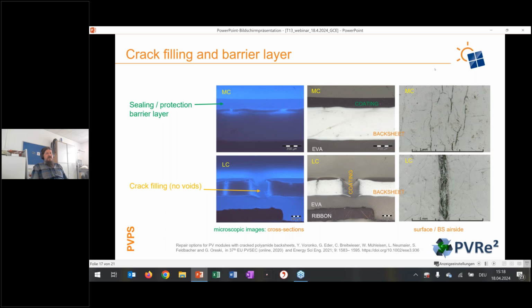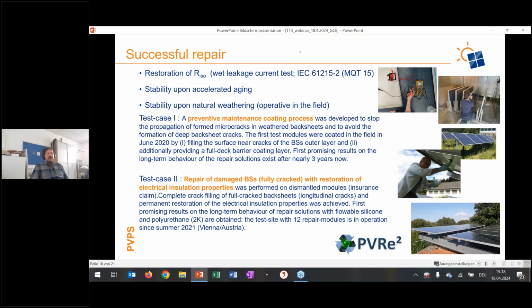As I already teased, we were successful. We could show that both of our coating solutions sealed the crack and also added an additional protection layer on top of the whole backsheet. So we really did the job there. We were successful, and additionally, we could also restore the wet leakage insulation of the PV module with that coating. The coating showed great stability upon accelerated aging tests, where we did especially damp heat and thermal cycling in order to see if there are chemical changes in the coating or if it shows delaminations or mechanical failures.